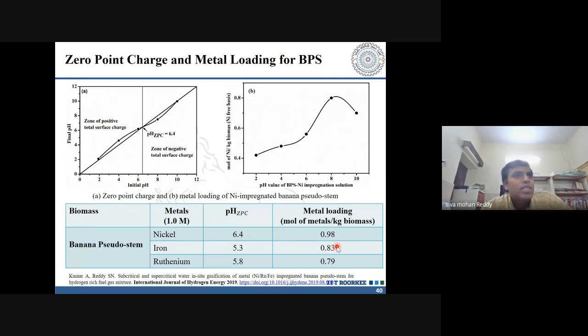So what we are doing in this process is replacing these alkalis and alkaline earth metals with the metals that we are talking about, in the form of nanometals, like nickel, iron and ruthenium. So these metals replace the alkalis that are present in your biomass, and this is how typically your treated biomass looks, right? You have a biomass initially, and then when we impregnate it with nickel, it is converted to something like this, where you are eliminating your alkalis and alkaline earth metals during the impregnation process, and replacing them with the metals that you have loaded. Okay.